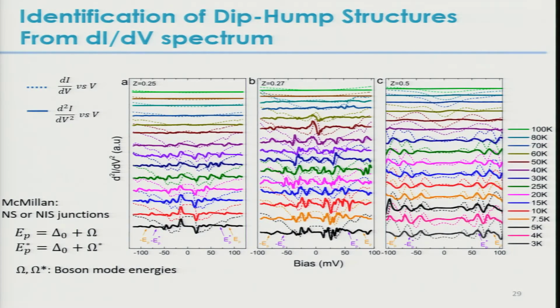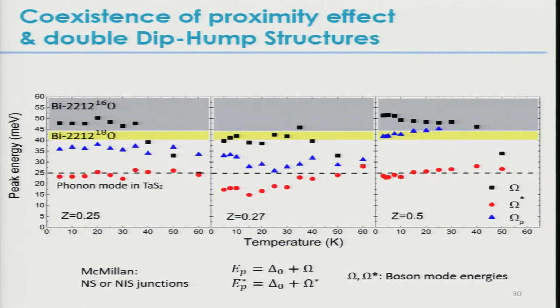You can see that we did a lot of spectroscopy in identifying these features. And basically, we see 2 boson modes, 2 peaks due to bosons, one which is already known for Bisco, and the other one which has something to do with the CDW in there. So there's a boson mode that we can recognize in our tunneling data that's visible on our IV spectra. And I won't go into detail, except that one of these modes overlaps this mode here. This is for different transparencies.